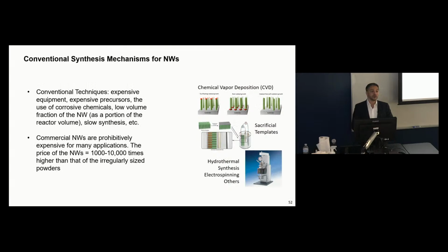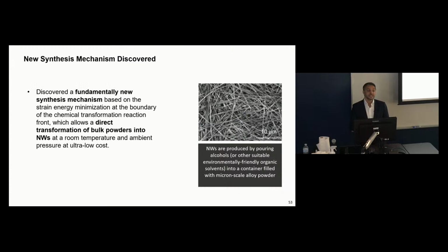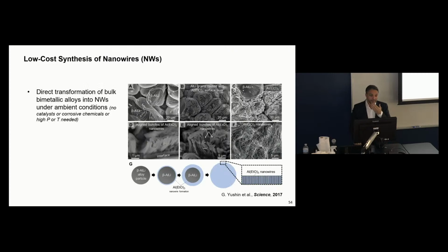And so there are multiple conventional ways to produce the nanofibers, but unfortunately, they all are very expensive. And so they're prohibitively expensive for battery applications, particularly for electric vehicles. And so we discovered a fundamentally new synthesis mechanism based on minimization of the strain energy at the boundary of the phase transformation that allows us to transform bulk powders into nanowires. To simplify it, essentially, you can put your powders in a bucket, put some solvent, and then form nanowires in a few hours, a few days. As simple as that. And we demonstrated this process some time ago. We published a paper in 2017.